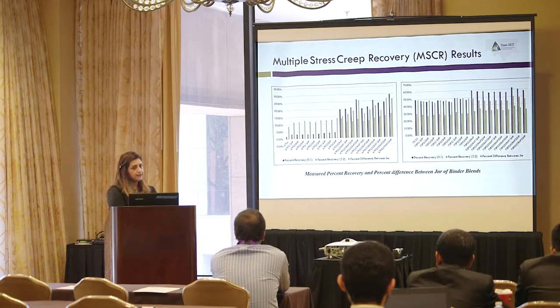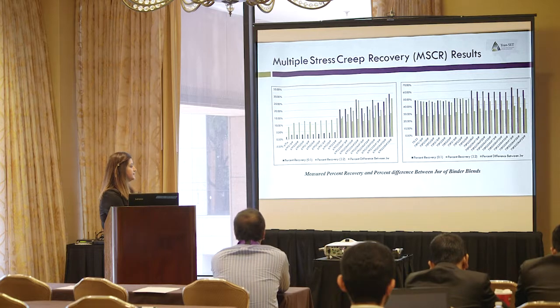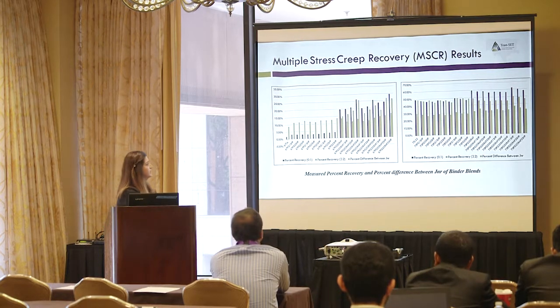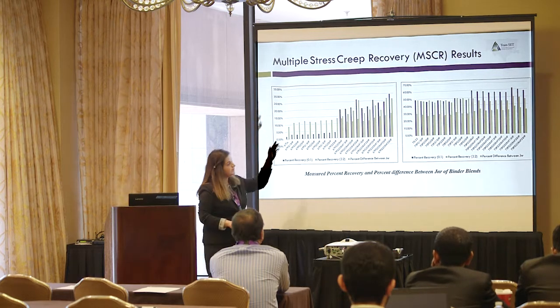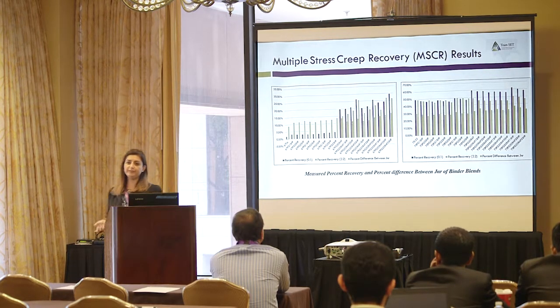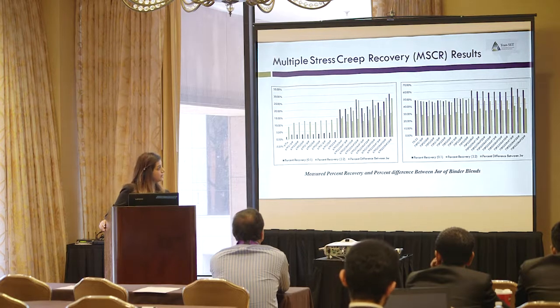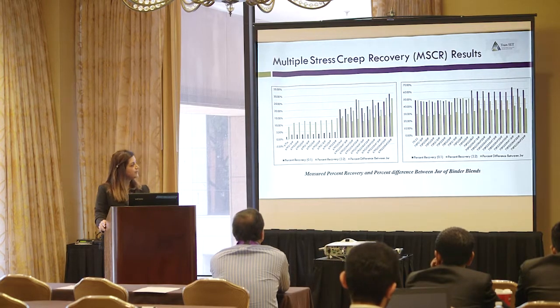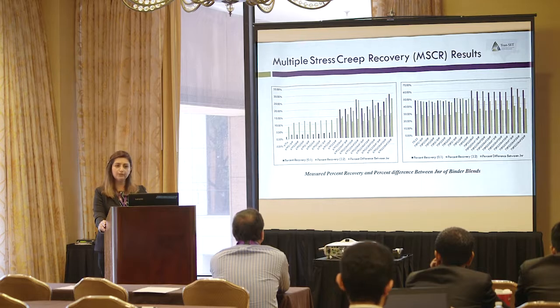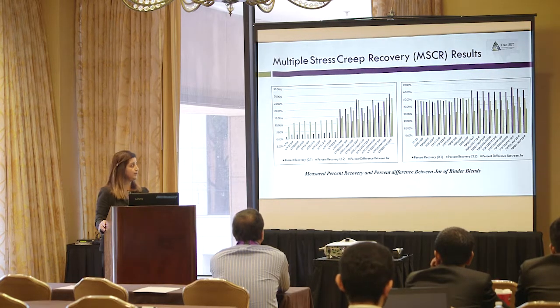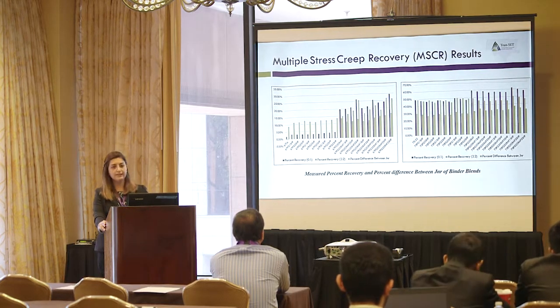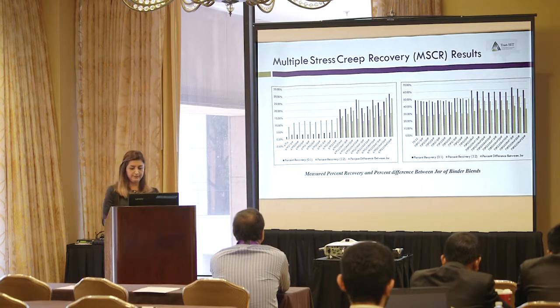We evaluated the elastic behavior of the binder blends using the MSCR test. Addition of self-healing material to the unmodified binder showed an increase in elastic recovery of the binder blends. This increase was further continued with 1 hour of UV exposure and 48 hours of UV exposure. But for binder blends prepared with 70-22, which is a polymer modified binder, we saw a decrease in elastic behavior of the prepared binder blends.